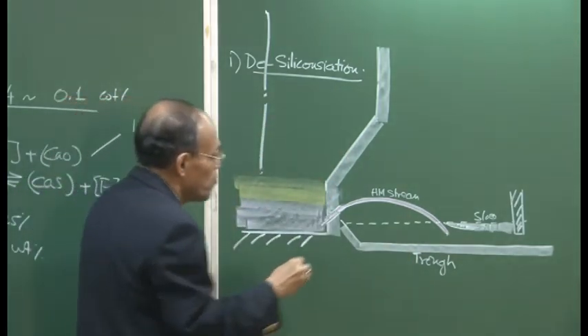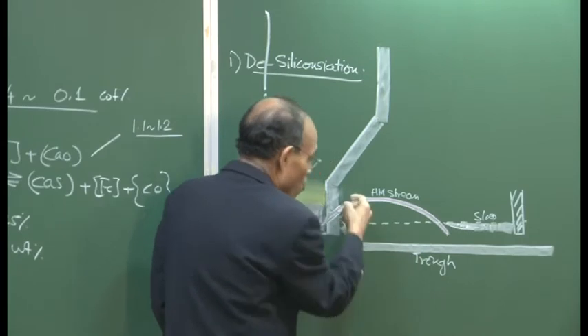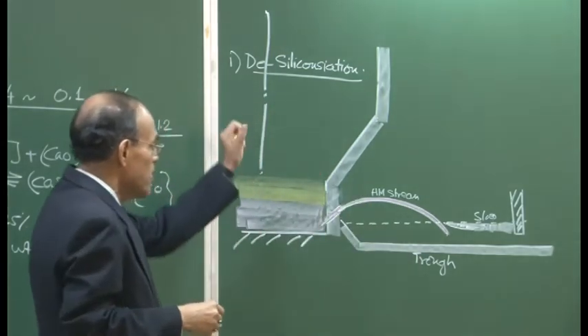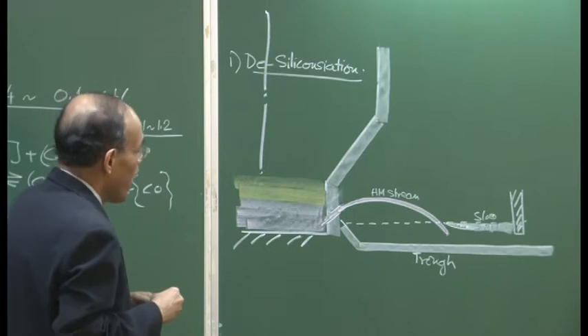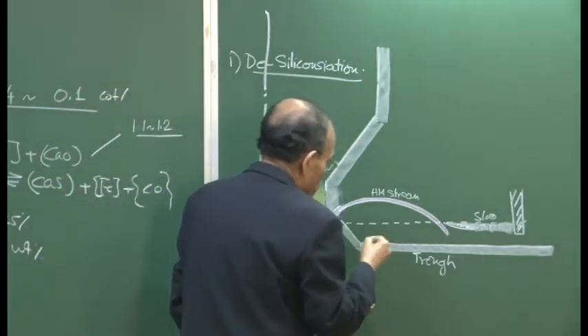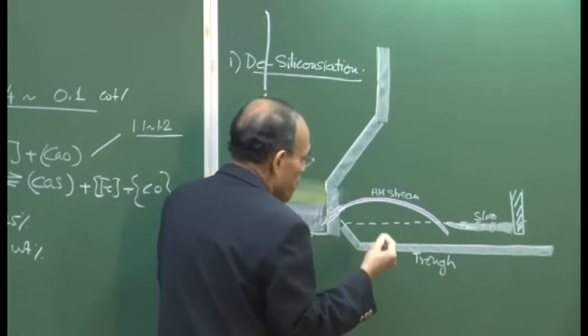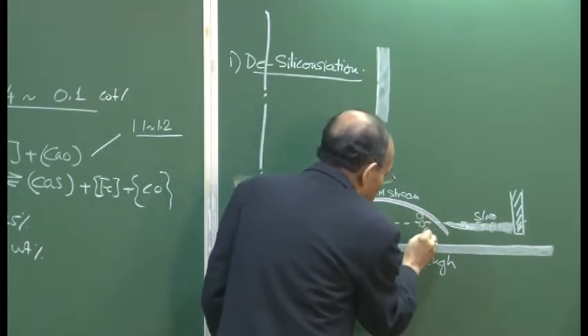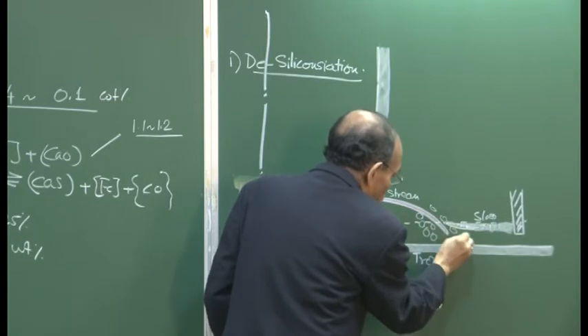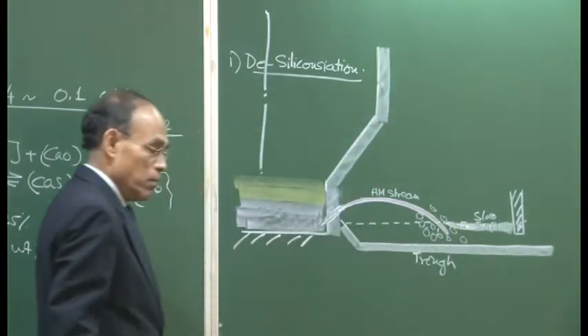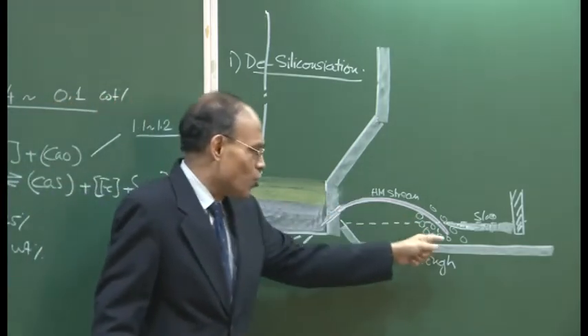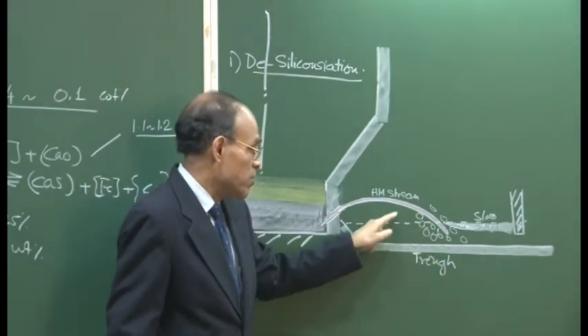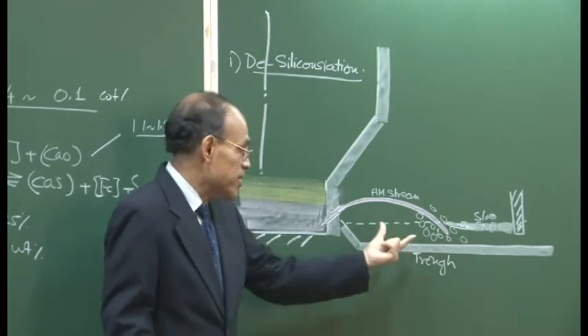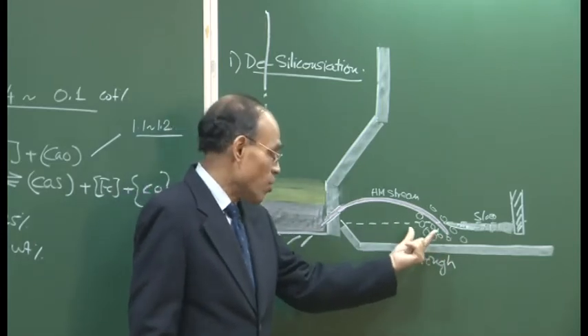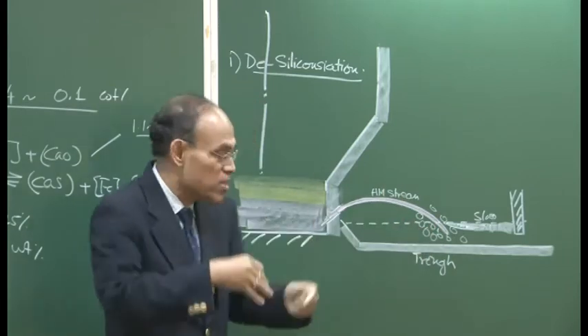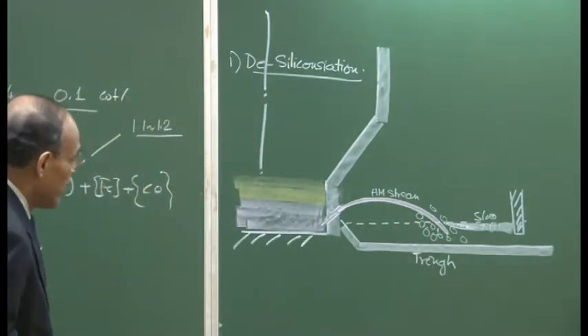And when molten metal flows like this, there is an enormous amount of molten metal coming out per minute, maybe 100 tons or something like that. Small blast furnaces, maybe 50, 55 tons per minute. So we have air bubbles also, which are entrained. There is a huge amount of kinetic energy of the stream, and a very good amount of stirring going on here. As you can see, slag, metal and gas are mixed, providing a huge amount of agitation.